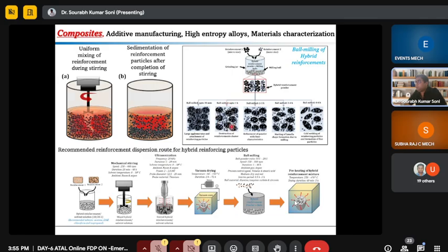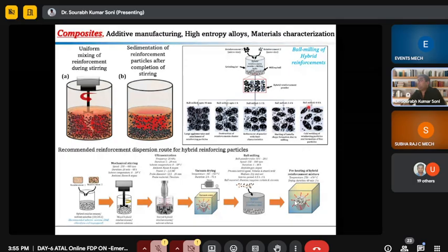After ball milling, some agglomerates are breaking. Further, we can see that there are very few agglomerates in 2-3 hours or 3-4 hours. What is going on in 4 to 6 hours? Very few agglomerates, but another phenomenon is coming: flattening. Flattening of the reinforcing particle, or destruction of the morphology of the reinforcement or matrix material. So this is the major problem.